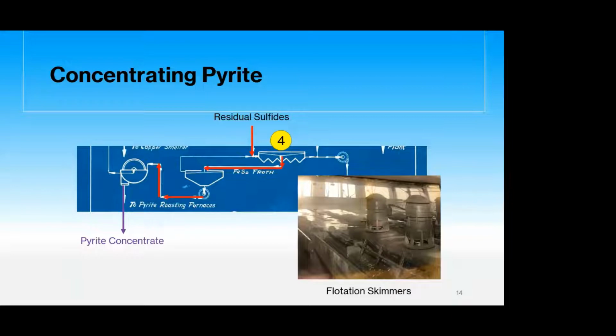Cornwall shipped the pyrite concentrate to Baltimore and to Sparrows Point, Maryland, where the concentrate was roasted and then leached to remove and concentrate the cobalt. Cornwall became an important source of cobalt for use by the nation as an iron alloy in armor plate and armaments, just in time before and during World War II and the Korean conflict.